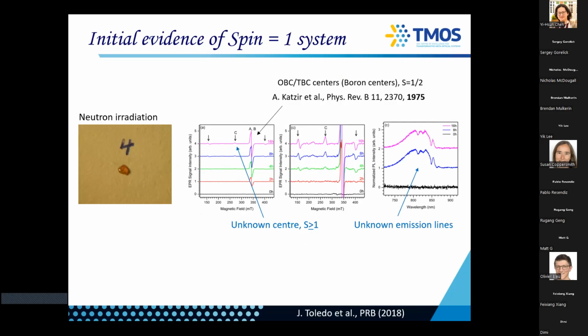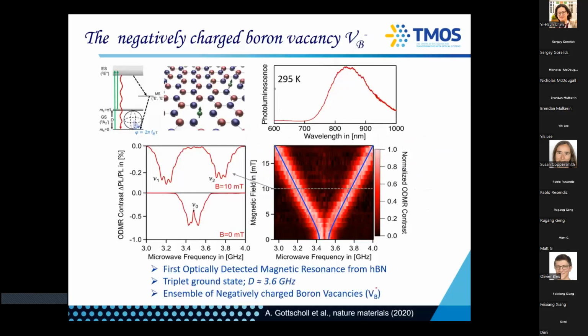Now, of course, when you see this coupled with your EPR and it scales with the dose, you know that you're working on an ensemble of high spin defects. And when you're doing an ODMR measurement, you don't know where to scan, but you just do a blind sweep. So we swept from 0 to 6 gigahertz. This was done in the group of Vladimir Dyakonov in Würzburg. And this was interesting because I was literally calling every single collaborator that was doing NV work and asking them, can you please do a scan for us? Because we don't know how.